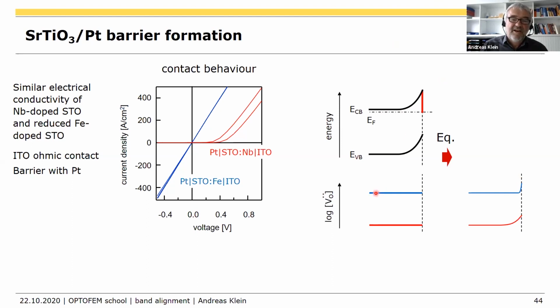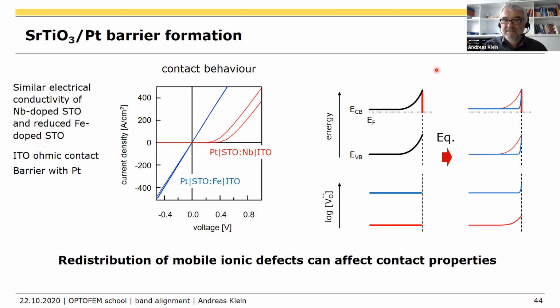And if you have already a lot in the bulk, the enhancement will become so high that in principle you make a metallic material. And at the end, with the iron doped strontium titanate, which has a lot of oxygen vacancies, the movement of the oxygen vacancies towards the interface makes this barrier extremely narrow. And that means you don't get a barrier. So you need maybe some 100 degrees C in order to get the oxygen vacancies mobile, but that is something which you have to consider. So if you have mobile defects, and that depends on the temperature and the kind of the defect, you can also substantially modify your barrier height.